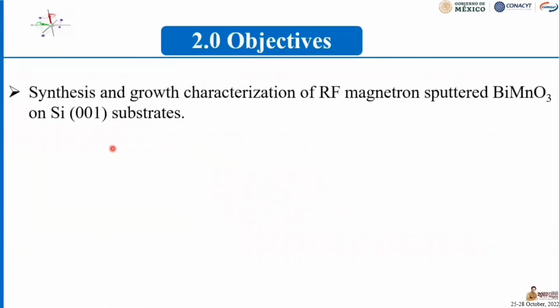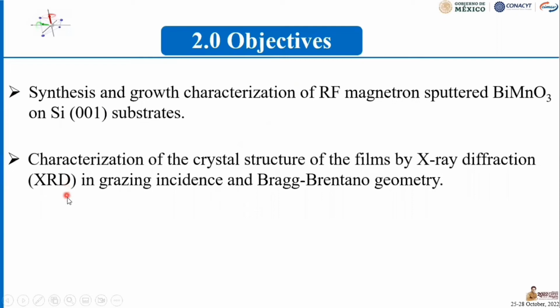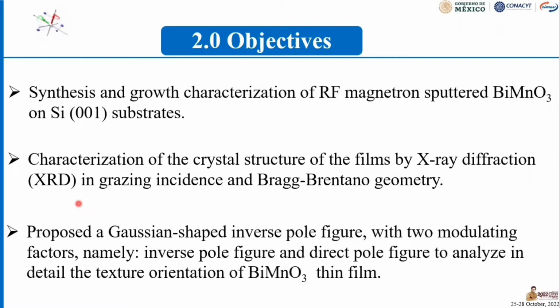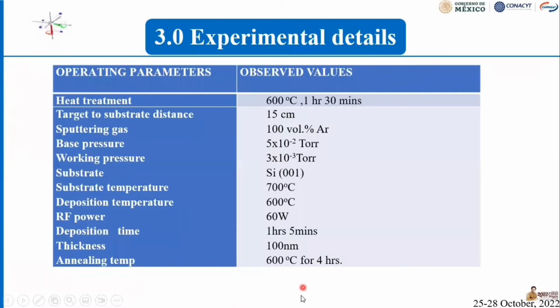The objectives are to synthesize and grow bismuth manganese oxide on a silicon substrate by radio frequency magnetron sputtering. Then, characterization of the crystalline structure of the films by X-ray diffraction in grazing incidence and Bragg-Brentano geometry. We also propose a Gaussian-shaped inverse pole figure with two modulating factors, namely inverse pole figure and direct pole figure, to analyze in detail the orientation of the bismuth manganese oxide thin film.